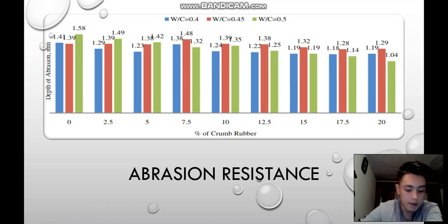Abrasion resistance. In this table you can see the abrasion depth in millimeters against the percentage of tire dust. It can be deduced that the smaller the amount of tire powder, the greater the abrasion depth, with the water cement ratio of 0.5 being the one of greatest depth.